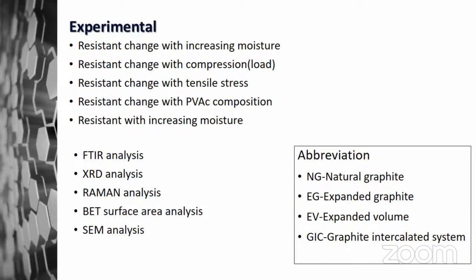We also compare the resistance change with PVAC composition, because with higher PVAC composition, that means the expanded graphite ratio is low, that will tend to decrease the conductivity and increase the resistivity. Also the resistance with increasing moisture, because after the adsorption of moisture, that will also affect the conductivity of the composite material. For the expanded graphite, we did FTIR analysis, XRD analysis, Raman analysis, BET surface area analysis, and scanning electron microscopy analysis.